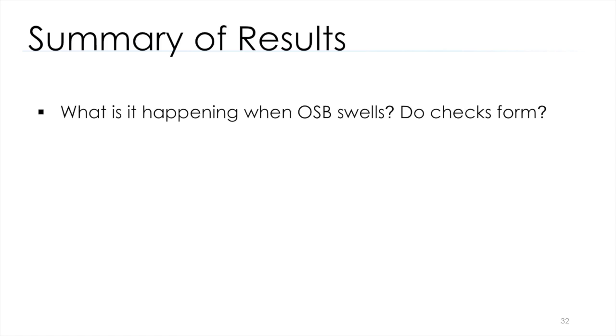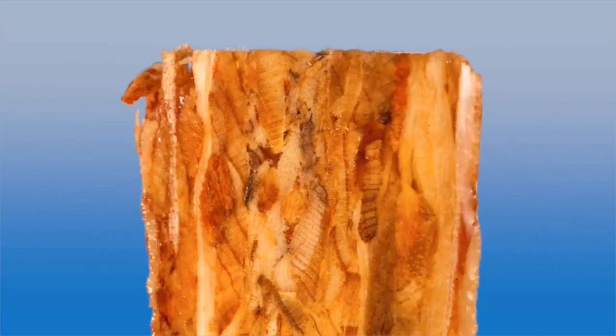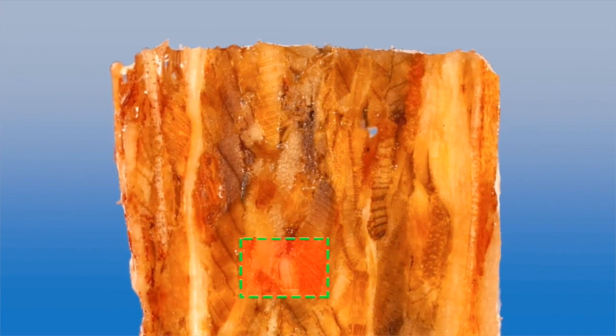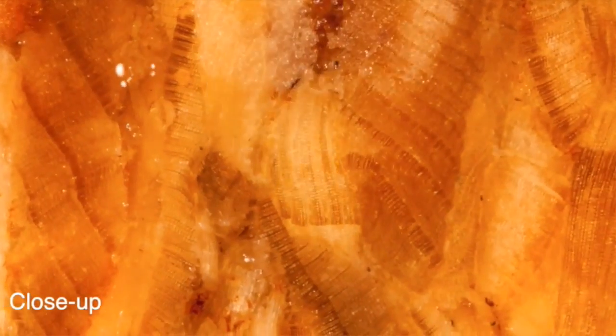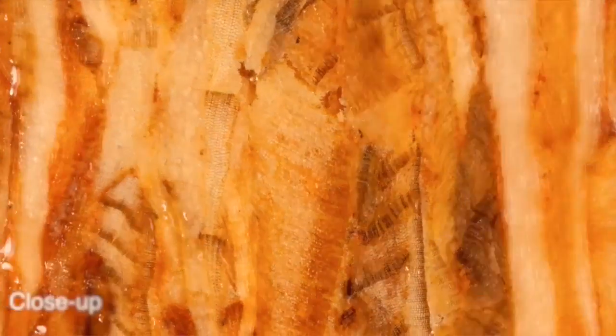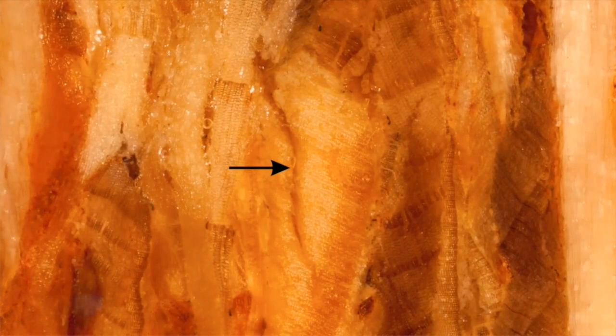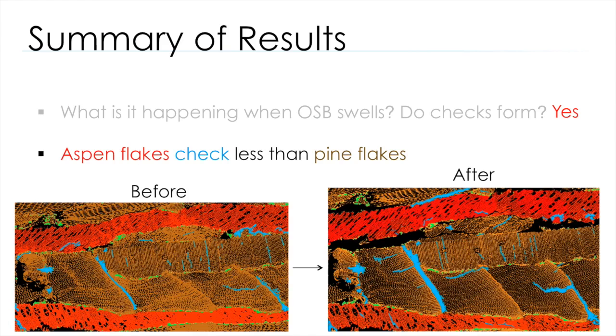Now, I would like to summarize the main findings of this study. What is happening when OSB swells? Do checks form? Yes, we did see significant checking of OSB. Unexpectedly, we found that checking was occurring during wetting when the OSB was swelling. That is the opposite for solid wood, which according to the literature only checks during shrinkage. Checking occurred less commonly in aspen flakes than pine flakes, as you can see on the flakes highlighted red, representing aspen. From this image, we can also see the partial recovery of deformed aspen vessels.